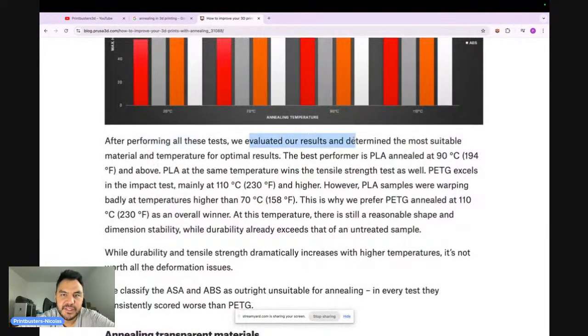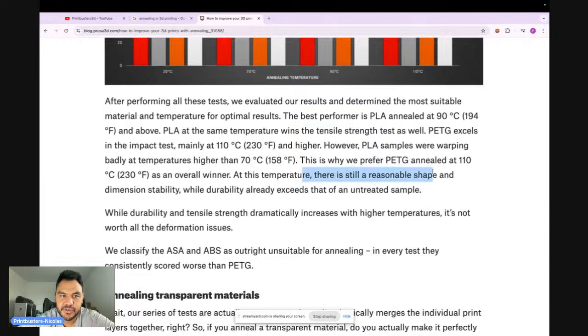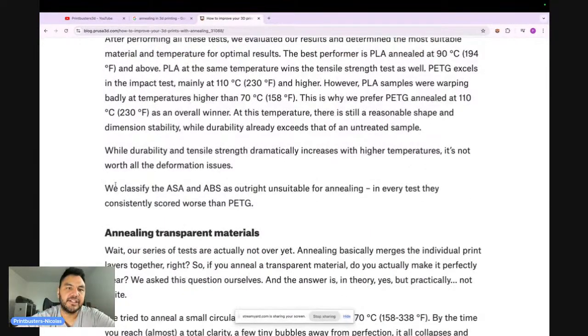After performing all this, we evaluated the result at this temperature. While durability, we classified the ASA and ABS as outright unsuitable for annealing. In every test, they consistently score worse than PETG. Yeah, okay, so maybe that's the reason why we need to do a little bit of some theory here. ASA and ABS are not going to crystallize.